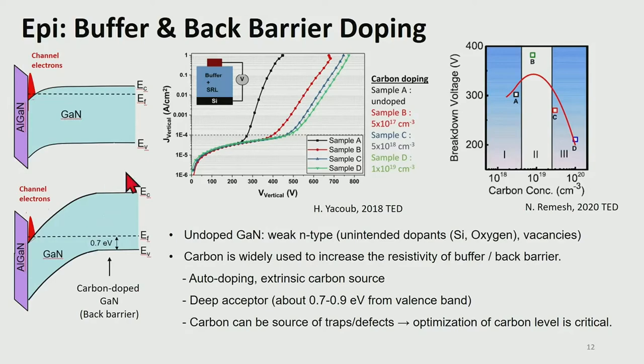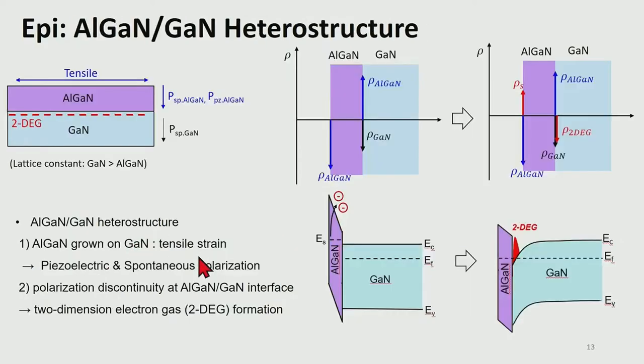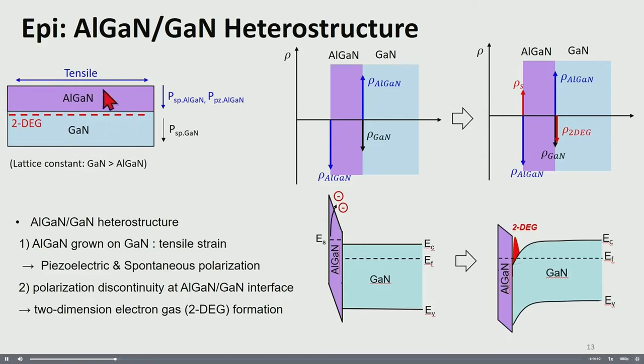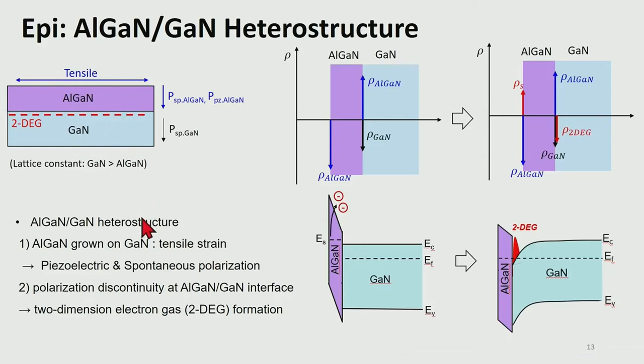So once the back barrier growth is done, now the next step is the top heterostructure. For the gallium nitride channel, we typically don't do any doping to maximize electron mobility and also minimize the number of traps. And the gallium nitride channel is capped with the AlGaN barrier. So the lattice constant of the AlGaN barrier is smaller than the gallium nitride. So if you grow the aluminum gallium nitride on top of gallium nitride pseudomorphically, the top AlGaN barrier gets tensile stress. And here, the polarization field that we discussed in the crystal structure part plays a very important role.